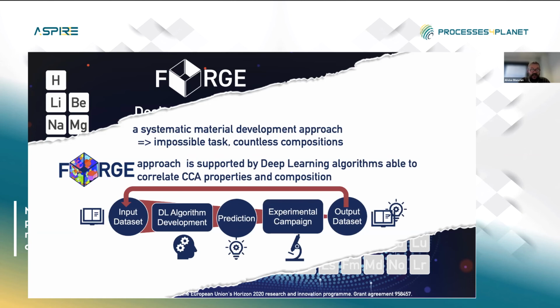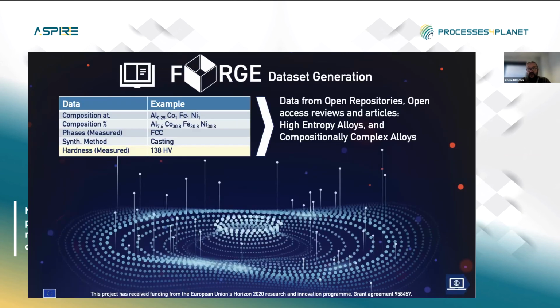So clearly, the starting point for this exercise is data from open repositories and data from other experiences that are in the literature for high entropy alloys and compositionally complex alloys. From this, we can get information on composition, sometimes information on the phases measured, and something related to the production methods, and most importantly, the performance that we are looking into, in this case, hardness.